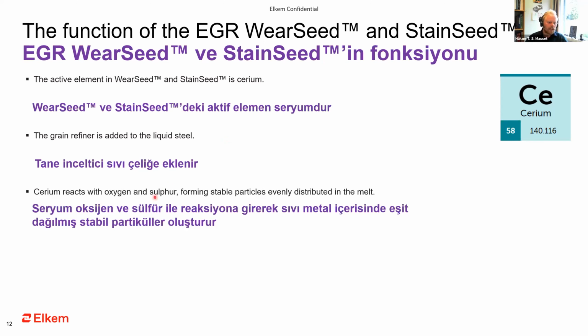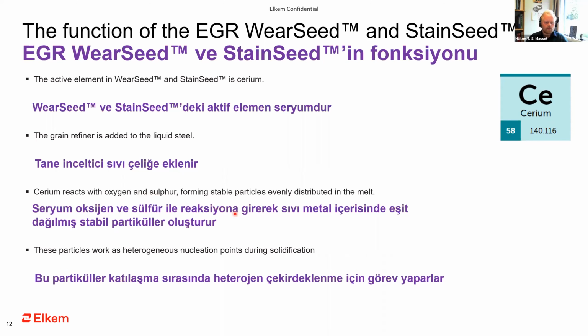And then the cerium will react with the dissolved oxygen and sulfur in your steel, and it will form stable particles evenly distributed in the melt. So depending on the amount of oxygen and sulfur in your steel, you will create cerium oxides, cerium sulfides, or even cerium oxysulfides. And of course, if you have some dissolved aluminium as well, you can get cerium aluminates in there. And all of these are suitable particles to promote heterogeneous nucleation and get grain refining in your steel. So, as I said, all these particles work as heterogeneous nucleation points during solidification.